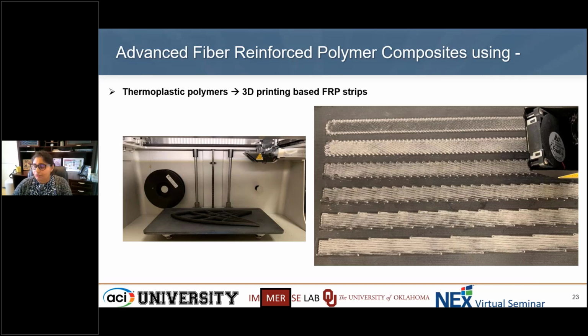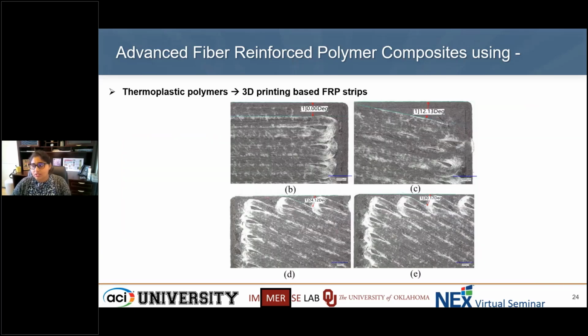The capability of these kinds of printers is the beauty of achieving different fiber orientations. We know that highly anisotropic materials such as this one are highly direction dependent. Their stiffness and strength change with direction. So the orientations are something that we can achieve with very high accuracy. And I can claim that because microscopic investigations that we've done show that if you're trying to achieve a 0-degree composite, so the fiber laid in a 0-degree fashion, you will achieve 0 degrees with 99% accuracy.